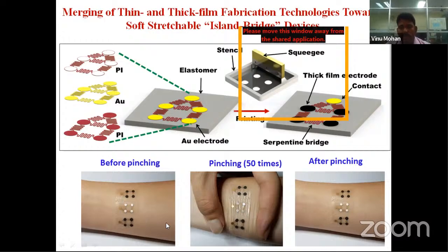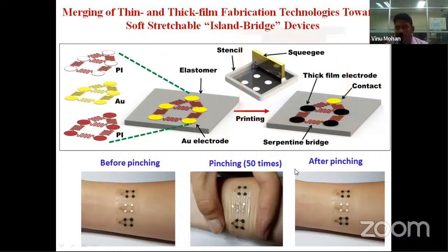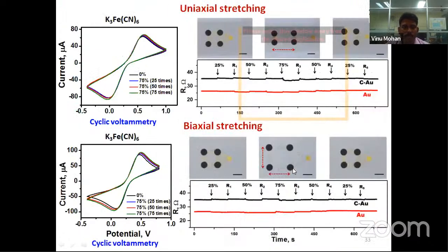So here this image shows we applied 50 continuous pinches, and later we stretched the device, but the device showed robust performance. Here we characterized the stretchability in terms of measuring the resistance. We applied different levels of stretching, and simultaneously we monitored the resistance change. As you can see, there is very little change in conductivity, and we characterized electrochemically also.